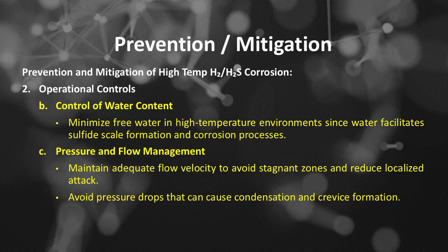Operational controls. Number B is control of water content: minimize free water in high-temperature environments since water facilitates sulfide scale formation and corrosion processes. Operational controls. Number C is pressure and flow management: maintain adequate flow velocity to avoid stagnant zones and reduce localized attack, avoid pressure drops that can cause condensation and crevice formation.